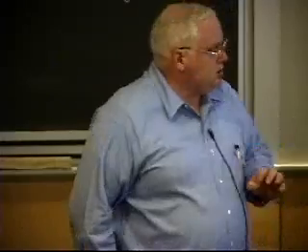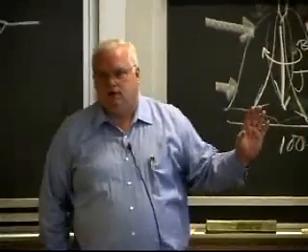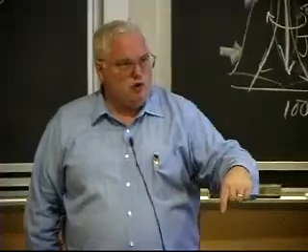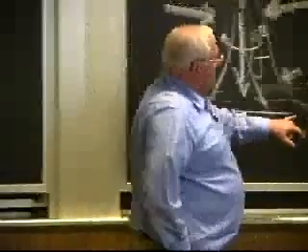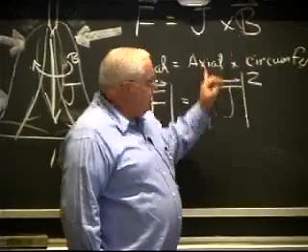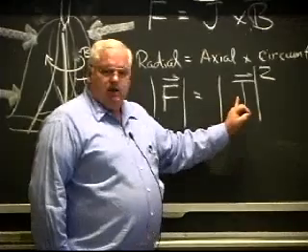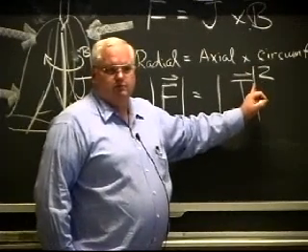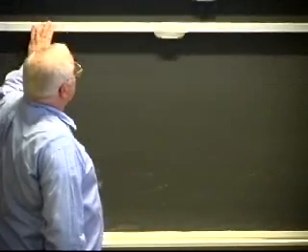Now, you can also use higher currents, which will give you more stiffness to that arc. You have more momentum going down, so it takes more momentum going crossways to blow it off. It turns out on welding power supplies, since the magnitude of the self-magnetic field B is proportional to J, the magnitude of the force in that jet is proportional to the current squared.